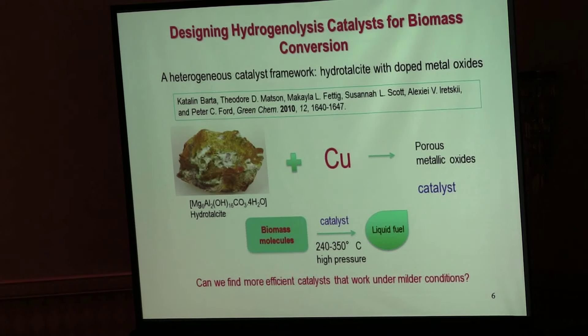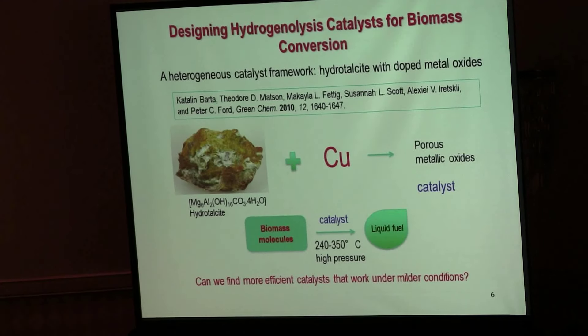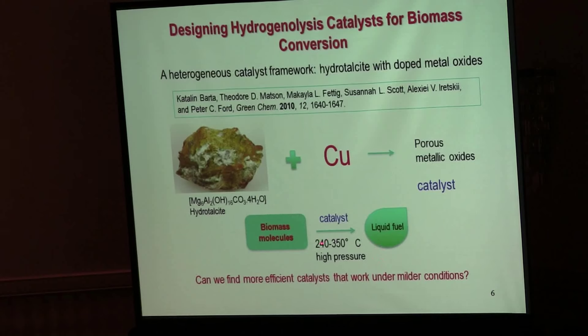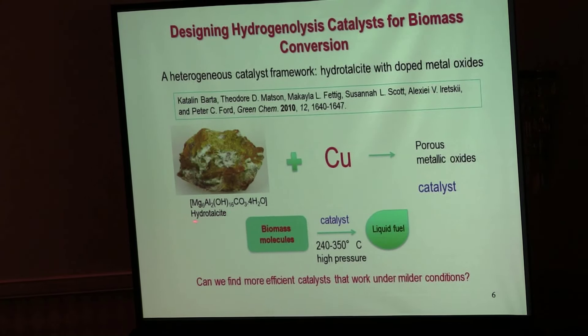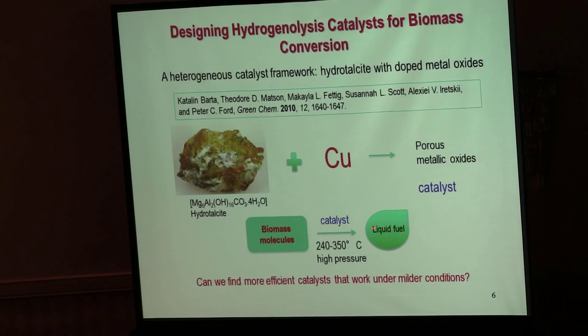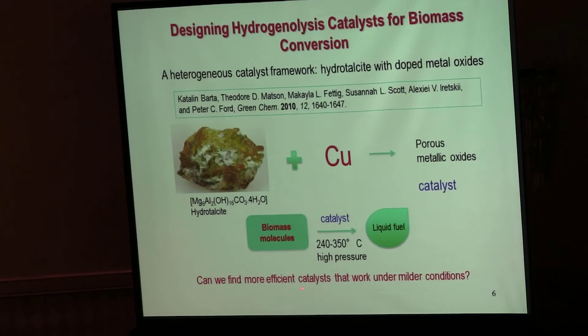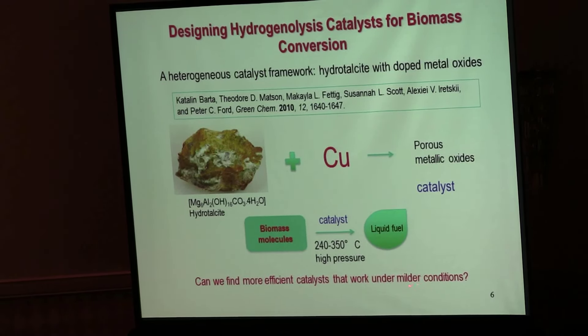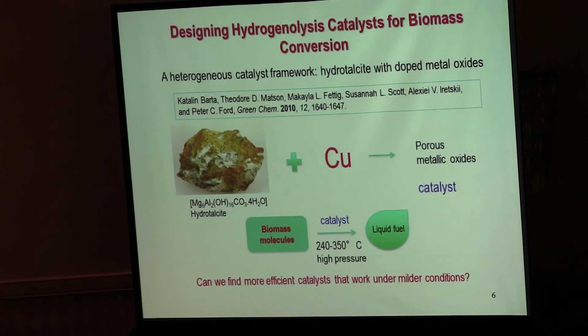There are many ways to degrade biomass, and one interesting catalyst I found in the literature was published by Professor Ford from UCSB. They use hydrotalcite doped with copper, and in a one-pot reaction at about 300 degrees C they can convert all the biomass — both lignin and cellulose — into liquid fuels. However, the temperature is relatively high and they're also using supercritical methanol at very high pressure. So the question is: can we come up with more efficient catalysts that work under mild conditions, which is a key consideration for green chemistry as well?